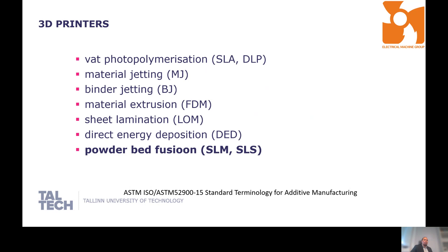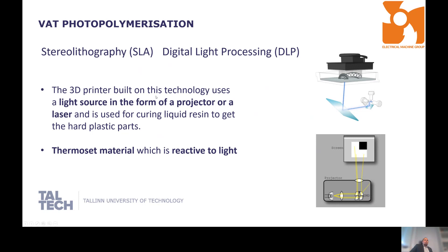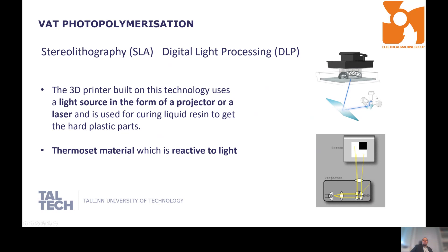What is a photopolymerization printer? Basically these are stereolithography or digital light processing printers that use thermoset material which is reactive to light. When light is given to the liquid, it hardens and we can lift out 3D objects. It has many advantages — we can produce isotropic material, it is the most precise printer available, gives very nice smooth finishing, and you can produce very detailed features with several different material characteristics. Sadly, you can only use thermoset materials, so they are not suitable for printing electromagnetic components.